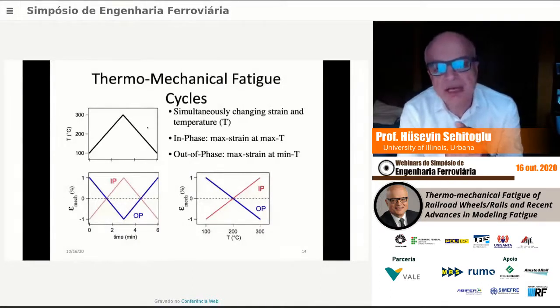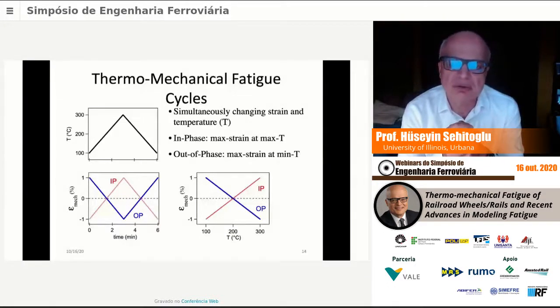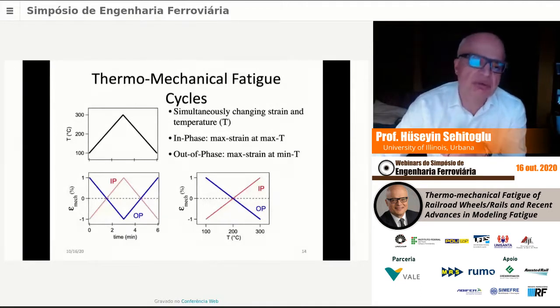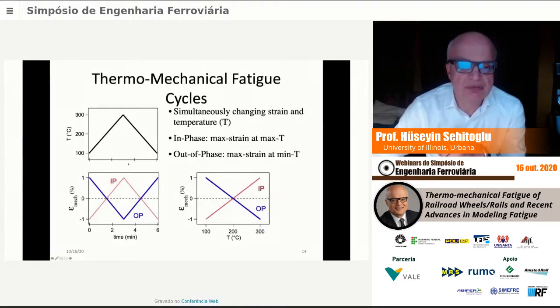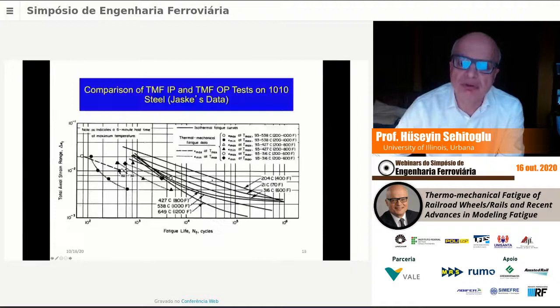Now, we start talking a little bit about thermomechanical fatigue. The thermomechanical fatigue is far more complicated, of course, than isothermal fatigue, you know, constant temperature fatigue. In thermomechanical fatigue, and this is just an example, we raise the temperature from a minimum to a maximum and then back to a minimum again. So we cycle the temperature, and this is mechanical strain versus time. This is temperature versus time. If the mechanical strain is in phase with the temperature, it's called in-phase thermomechanical fatigue. If the mechanical strain is out of phase with temperature, it's called out-of-phase thermomechanical fatigue. So if we plot mechanical strain versus temperature, the in-phase behavior looks like that, out-of-phase behavior looks like that. So when we try to conduct thermomechanical fatigue experiments, we have to be able to control strain and temperature at the same time. And this requires quite a bit of controls, quite sophisticated controls.